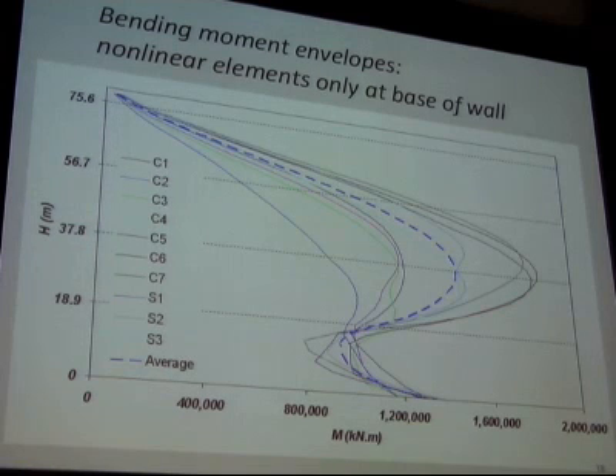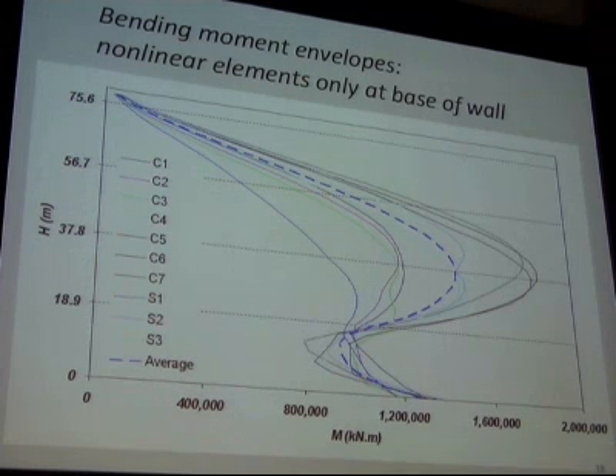Here's an example of a result that one of my students has done, where there are nonlinear elements at the base of the shear wall, which is commonly done. What you see in these moment envelopes from dynamic analysis is that you're developing huge bending moments at mid-height. But that's because these elements are modeled as linear. So that's how these moments can get large. And five or six years ago, I thought, boy, we really got to change the code because we're going to develop hinges at mid-height, and that's a problem.